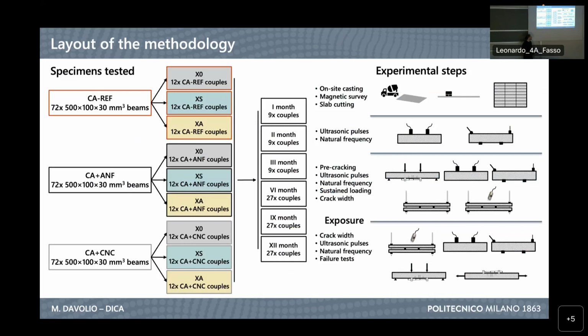produced, and we did these 2 different non-destructive tests that we then repeated afterwards, as you can see from the picture, at stage 2 and 3. Stage 2 is when, after the non-destructive measures, we pre-crack our specimen to induce the damage that the material has to face during its service life. And then, after damaging the specimen, we repeated the non-destructive measurements, and then we applied this frame, this steel frame for sustained load, and we analyzed the cracks on the specimens.